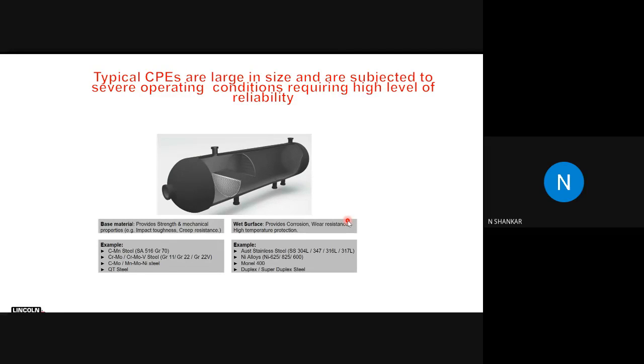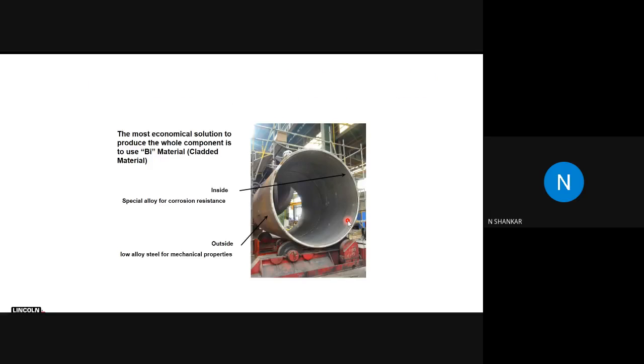For example, you need a base material with good impact toughness and good creep resistance, like manganese or chromoly vanadium steel. Also, on the inside of this process equipment, you need corrosion resistance and high temperature protection, which are slightly different characteristics for different materials, like austenitic stainless steel, nickel alloys, Monel, and duplex stainless steel. So manufacturing all of these using one complete material may be very expensive.